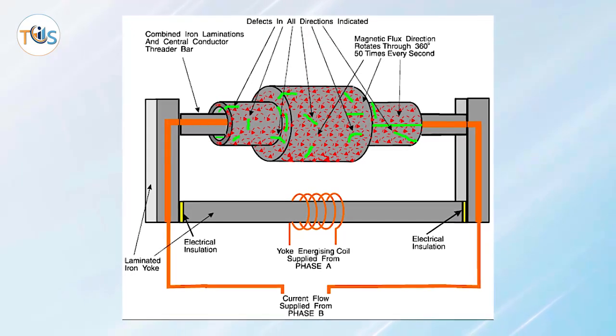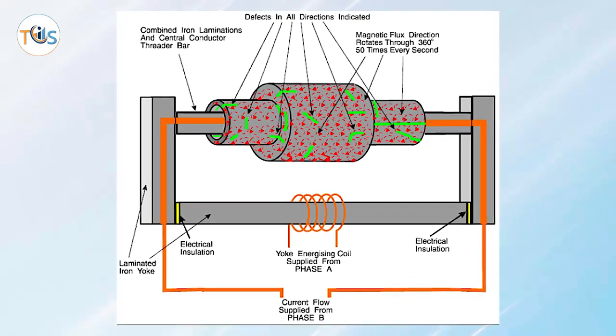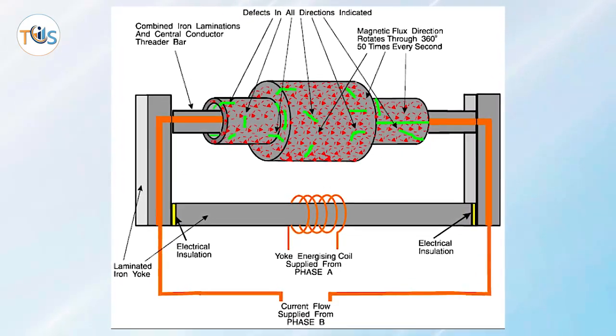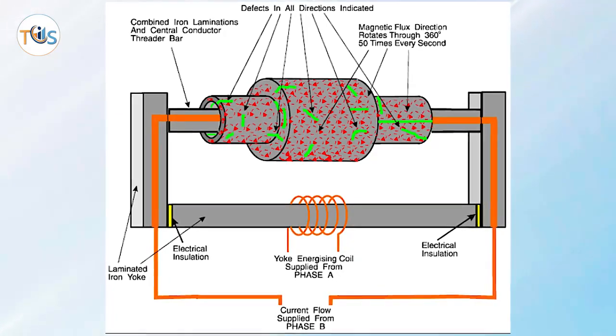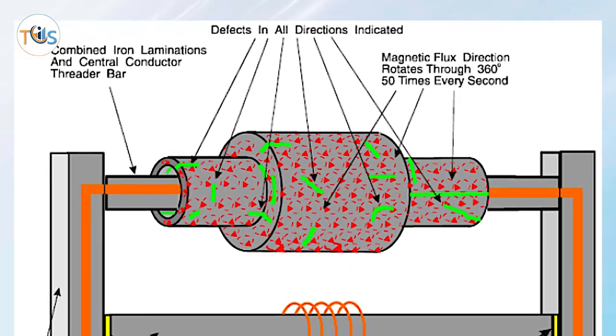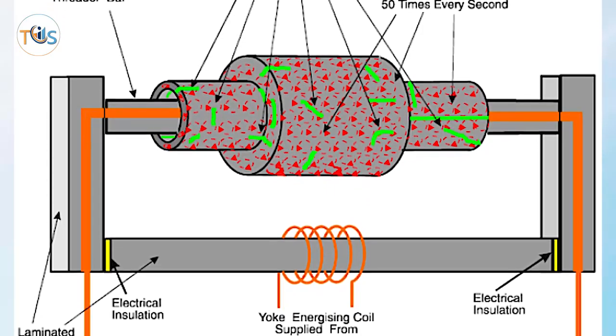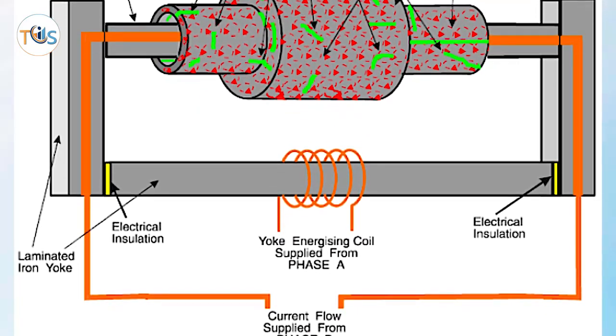Multi-directional Magnetization Technique. This is normally obtained using a three-phase current. One phase magnetizes in one direction whilst the second phase magnetizes in a perpendicular direction. Magnetization is accomplished by high amperage power packs operating as many as three circuits that are energized one at a time in rapid succession. The effect of these rapidly alternating magnetizing currents is to produce an overall magnetization of the part in multiple directions.